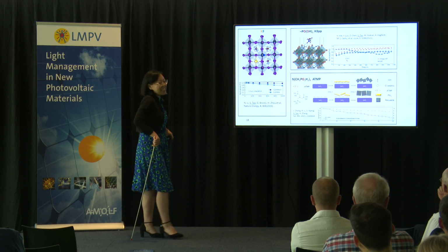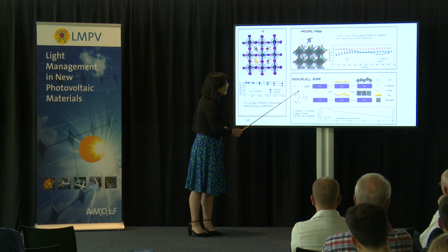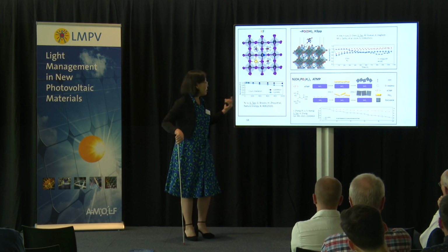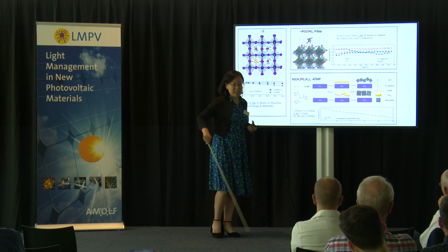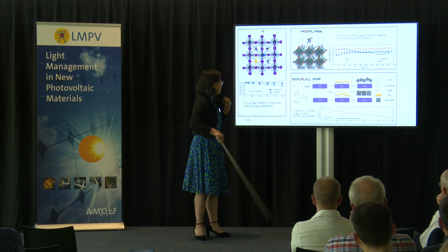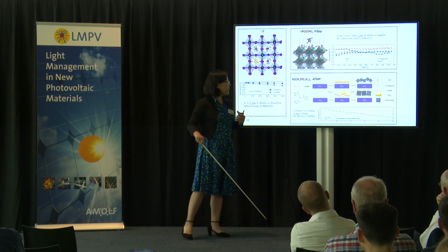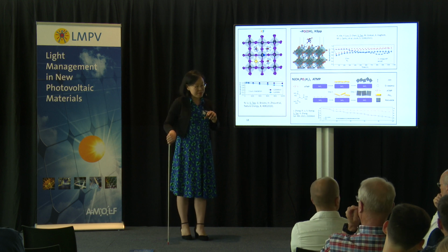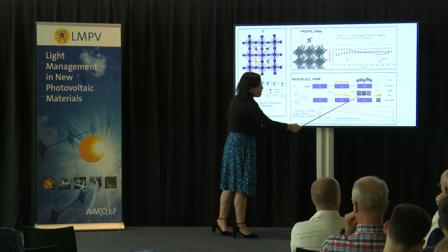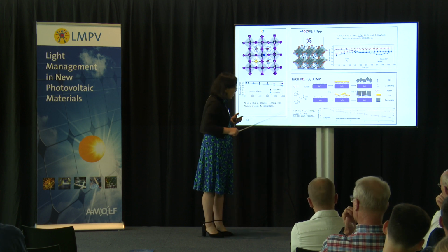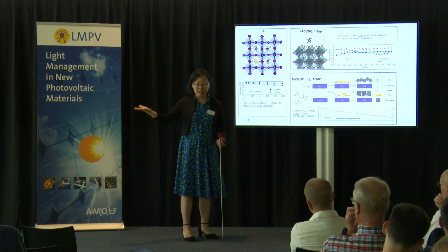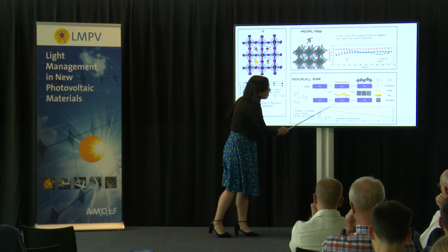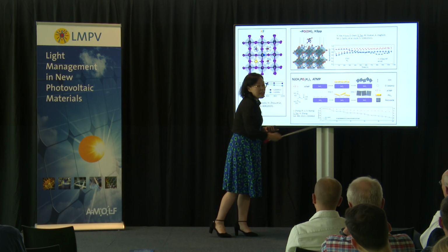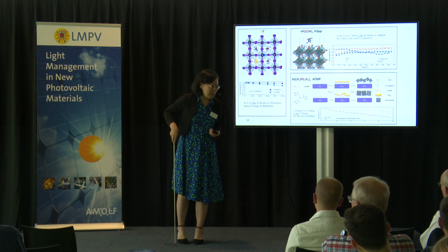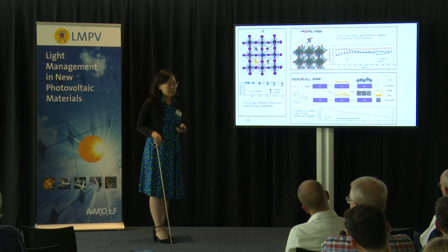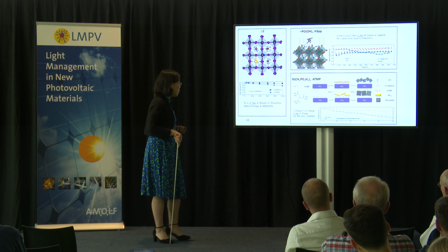Okay, another molecule that is even more complicated. This molecule has oxygen species as well, but it has 3 arms. This is very interesting, and it's been applied in the interface of the cells. What it does is it does several things together. When you put it on the tin oxide, on the one hand, it passivates the oxygen vacancy on the tin oxide. On the other hand, it also tunes the energy level alignment between these 2 layers. And if you pay attention to this small umbrella, all of them nicely form a layer on top of tin oxide. When we grow perovskites on top of here, we grow a very nice homogeneous film. That potentially reduces the defects. And by doing this, the additive altogether makes the cells more efficient and more stable.